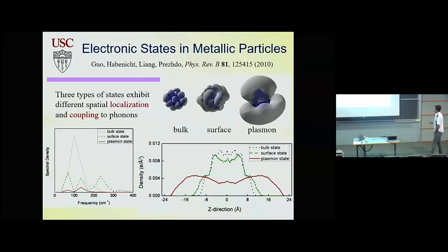But first I'd like to show you a typical small cluster. There are three kinds of states when you have a metallic cluster. There's a state that's localized in the bulk. Then there's a state that's localized on the surface. And then you have the state which you can call plasmon-like. And in plasmonic response, you have many orbitals of this type. You have a superposition of many states like that, and that creates a plasmonic band.